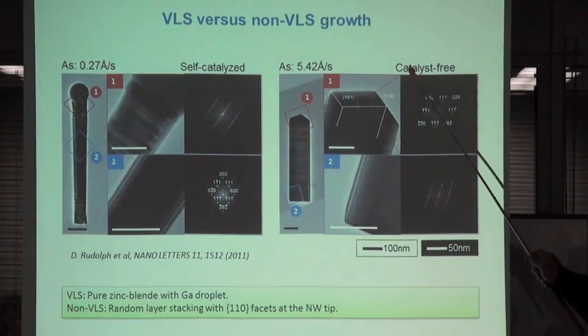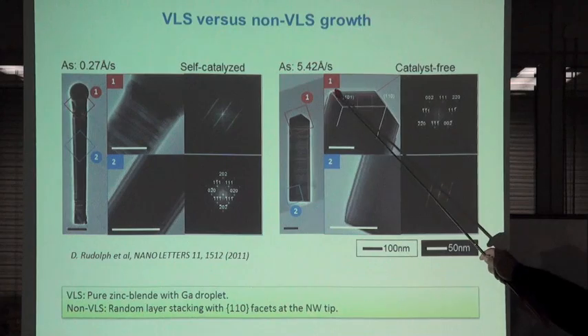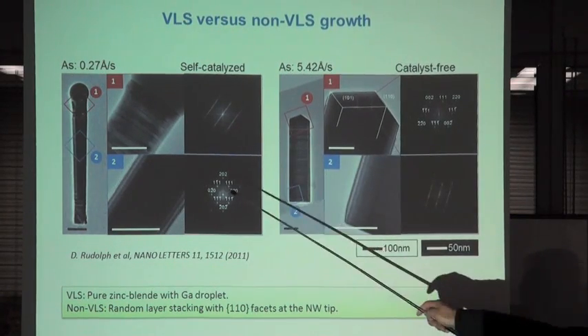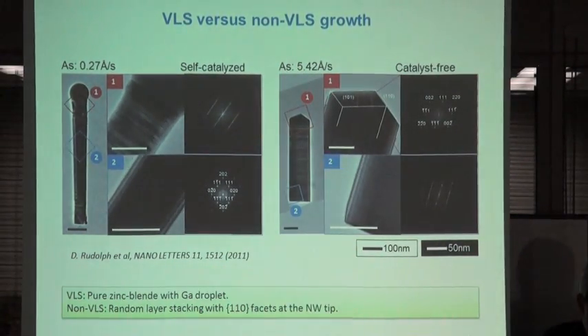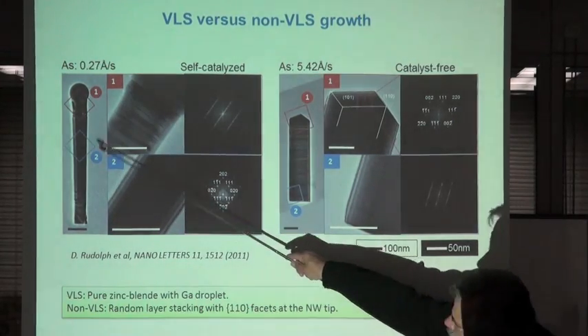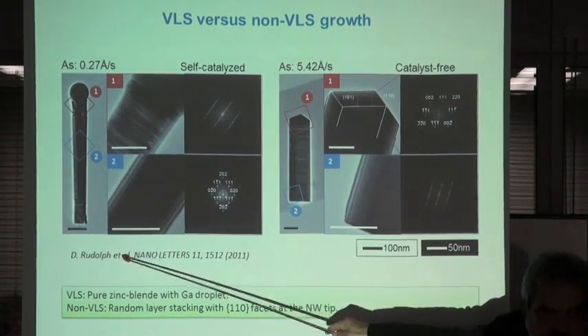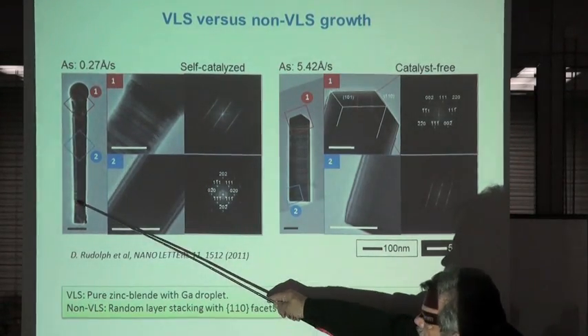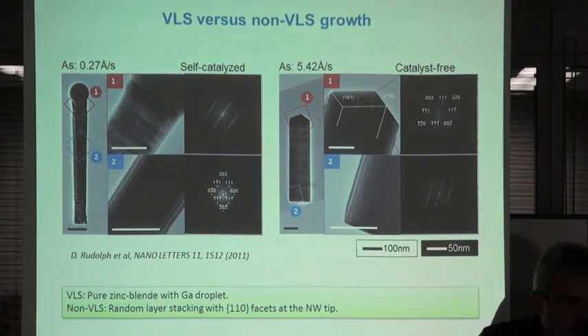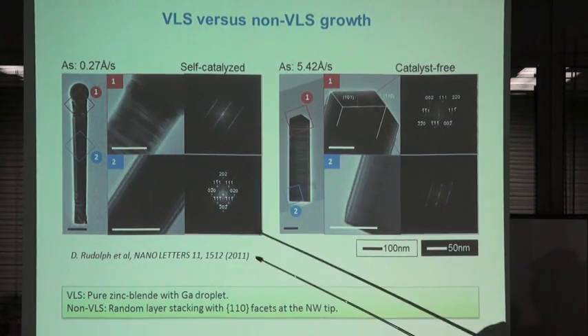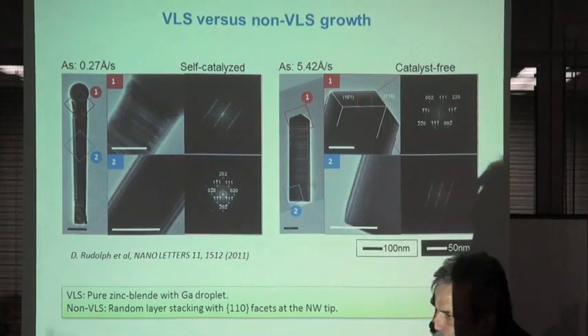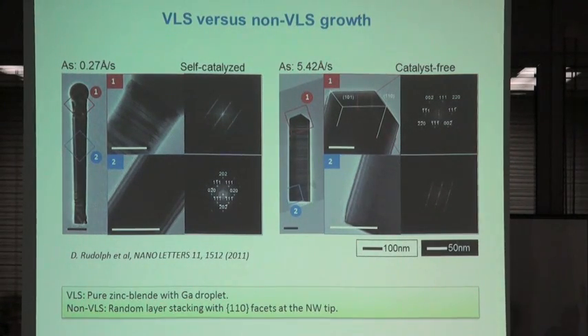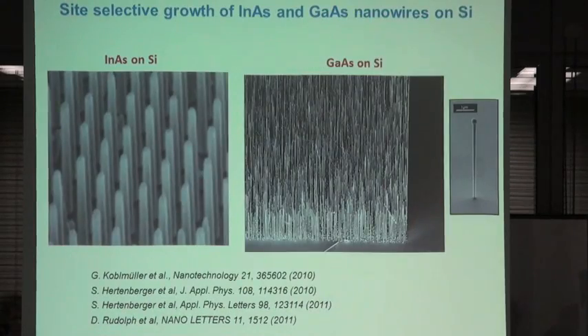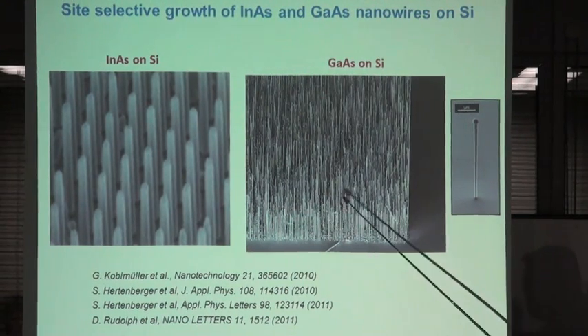And this again, you see, if you have this catalyst-free non-VLS growth, then you get facets at the end, and if you have the VLS growth, you get the droplet. And these nanowires, if they are grown in this mode, are over a long part single crystalline zinc blende in this case, and they have some defects at the beginning and at the end when we cool down. And at the moment we are embedding quantum dots in such a system, and we do a lot of optics and also transport in these nanowires. Actually, this is not the same scale because I didn't have the same kind of figures.